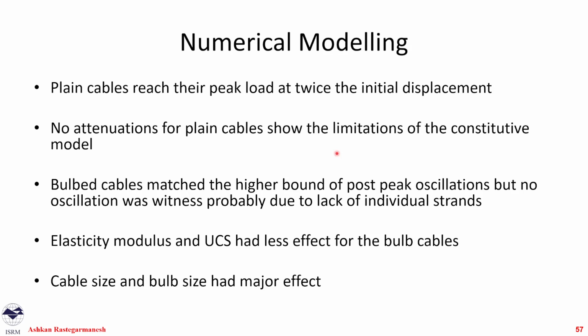In numerical modelling, we realized that with our plain cables, we were able to reach the plain cable peak values, but at twice the displacement. We didn't have any attenuation in the plain cables, which is probably a shortcoming of our constitutive models, which cannot dissipate the energy. With our bulb cables, we reached the peak and post-peak oscillations, but again, we couldn't match the oscillations easily. Again, that's probably constitutive model limitations.